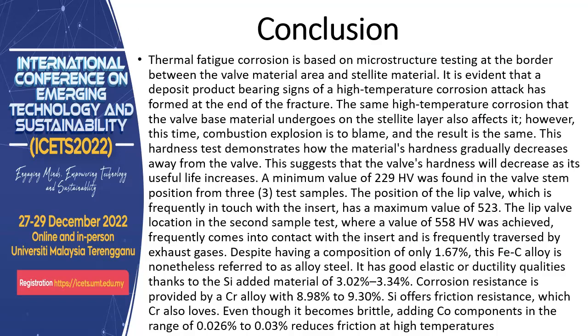Conclusion: the thermal corrosion is based on microstructure testing at the border between the valve material and stellite material. It is evident that a deposit product bearing signs of high temperature corrosion attack has formed at the end of the fracture. The high temperature corrosion that the valve material undergoes on the stellite layer also affects it. However, this time combustion explosion is to blame, and the hardness test demonstrates how the material hardness gradually decreases away from the valve. This suggests that the valve hardness will decrease as its useful life increases.